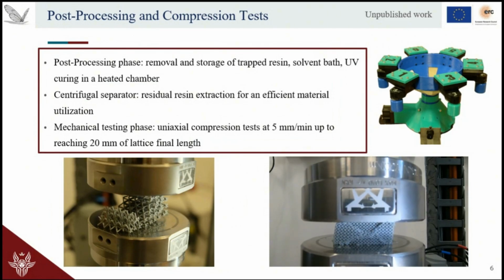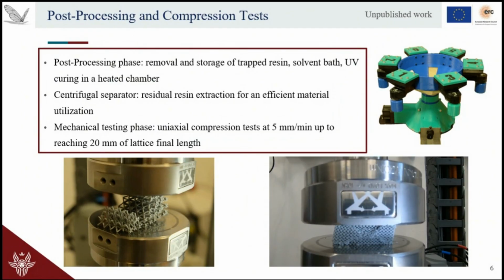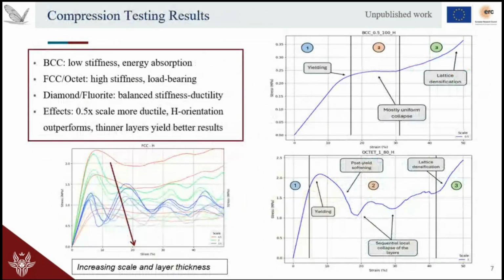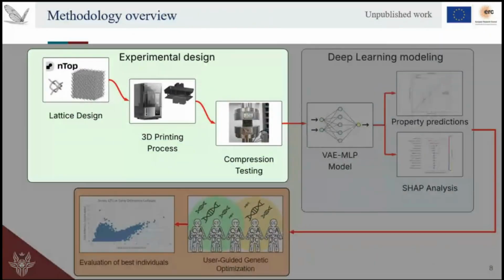So, since we are dealing with a lattice structure, they are very porous and they act as a sponge. So we have to separate the excess resin by using a centrifuge apparatus. So those are the mechanical results of the compression, and we can notice normal behavior of those lattice. So we have some bending dominating behavior, for example, in BCC, and some mixed behavior for fluorite and octet cells, but they are normal, and that's a good indicator that the print process was good and there are no anomaly detected. So that's for the experimental design.